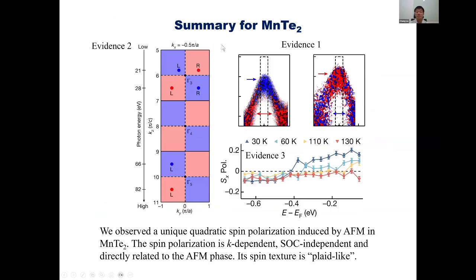So this is the summary of our work. We collected three different pieces of evidence to give the conclusion that the spin polarization is k-dependent and SOC-independent, and the spin texture is plaid-like. So we kind of discovered that some antiferromagnets have spin splitting.